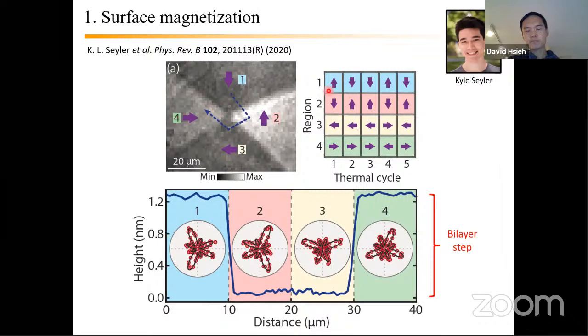You can see that as we thermally cycle through TNéel several times, the spin in region 1 and spin in region 2 are always anti-correlated. Okay, if one is down, the other is up. So really, you can look at the paper for details, but really there's this big region which we think we're really sensitive just to the surface magnetization. Okay.